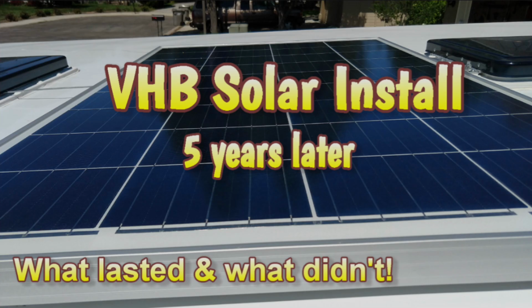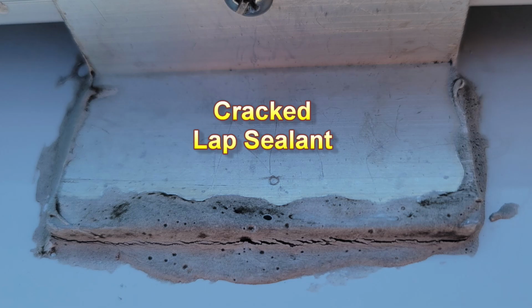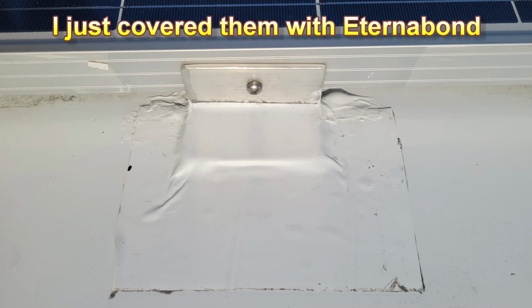What about long-term durability of these tapes and fatigue over many cycles? My experience is that VHB tape has held my panel firmly for 5 years, but the Dicor lap-sealant is showing some micro cracks, and I need to do something about that. I just covered my brackets and the aging Dicor with Eternabond tape. Really easy because you don't have to scrape off the old Dicor.